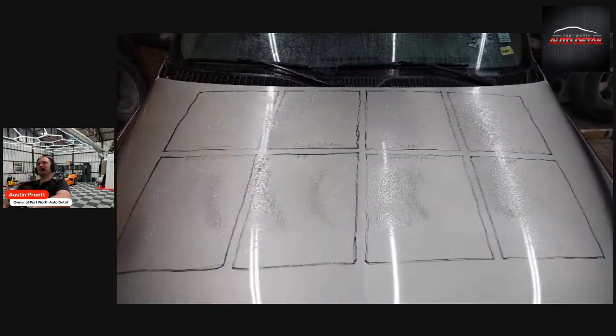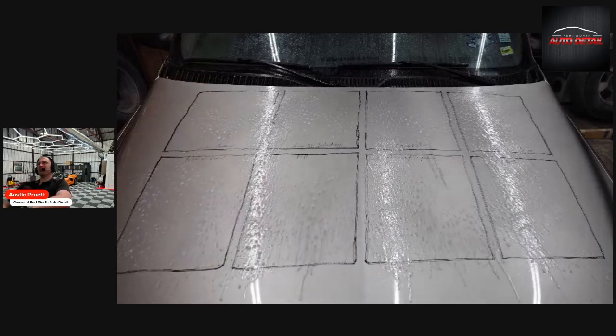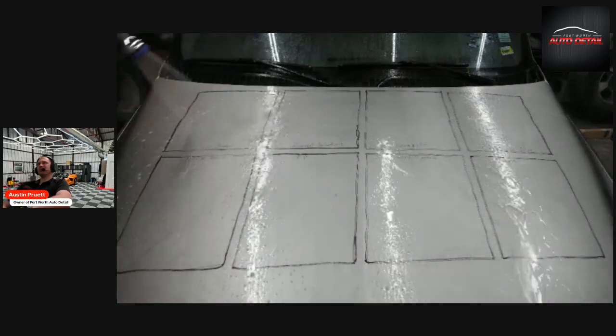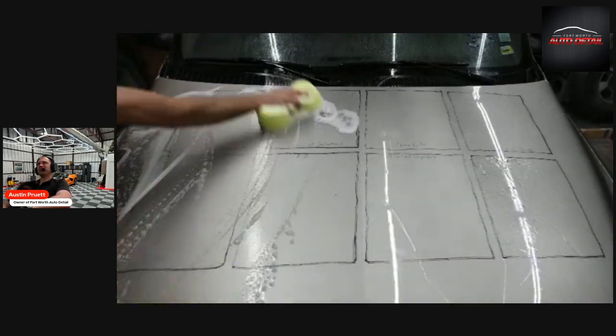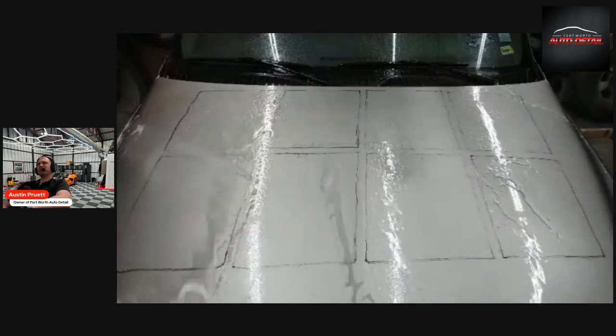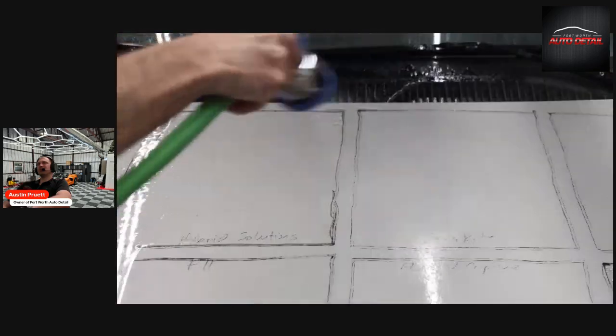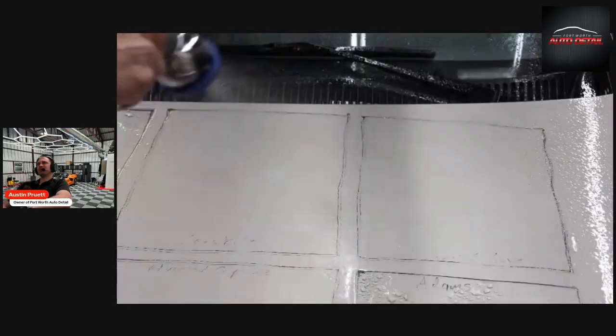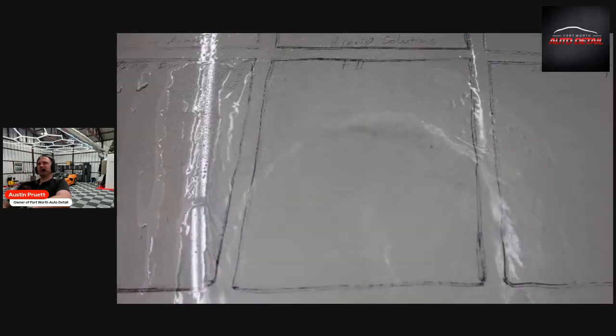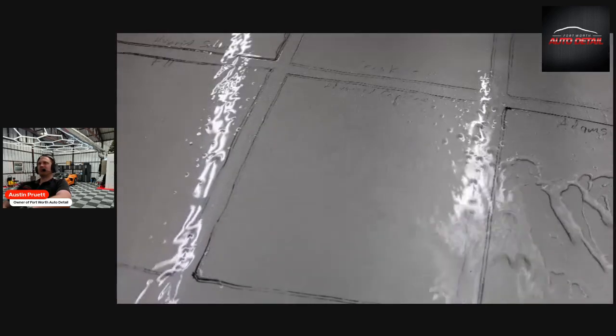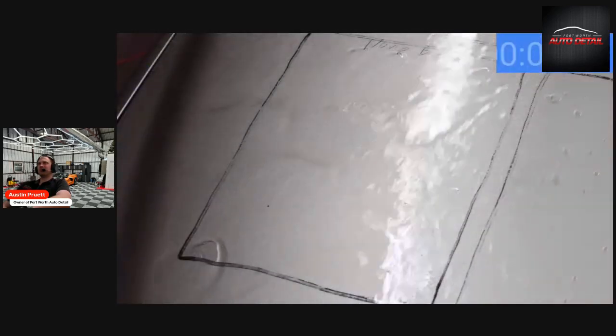I put together a review on degreasers a while back, and we'll see if any of these products can survive the best degreaser that I tested. I'll wash the test area once again with strip wash, just to make sure that all the degreaser has been removed. The first 4 products are spray and wipe coatings, and they all appear to be completely used up. The F11 and Advanced Graphene are also pretty much used up. So it comes down to the Nanobond and the Atoms.